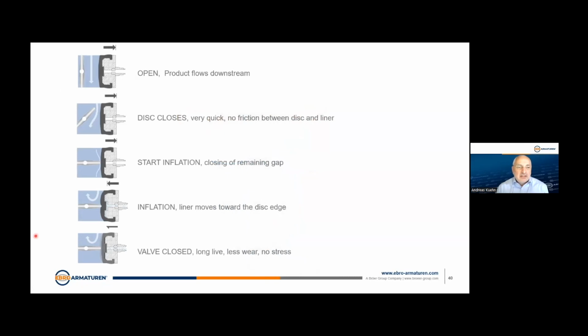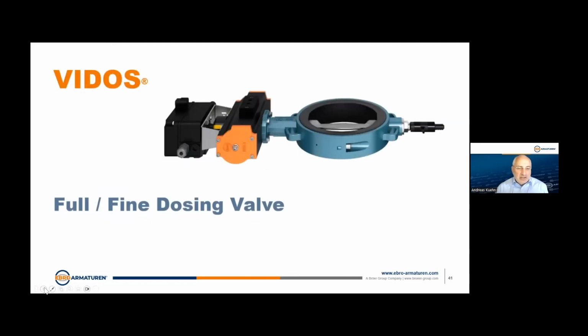We prevent that. We use a smaller disc. So when we close the disc, there is still a little gap. And then we press compressed air or nitrogen, depending on the process, and we inflate the liner. We press it against the disc edge, and we prevent the rub off when the disc is opening and closing. And so the lifetime, the lifespan of the valve increases drastically.